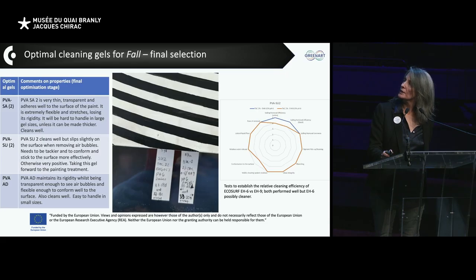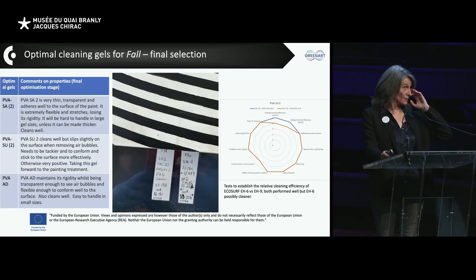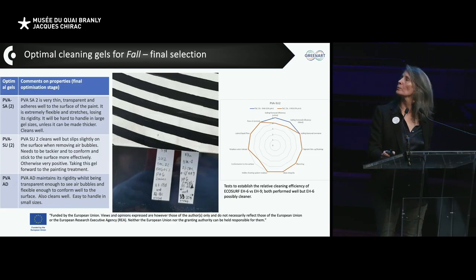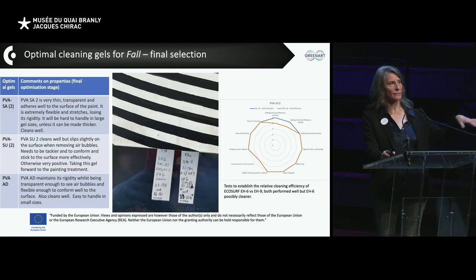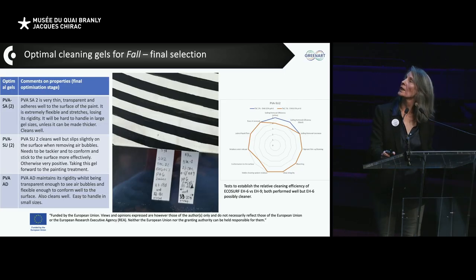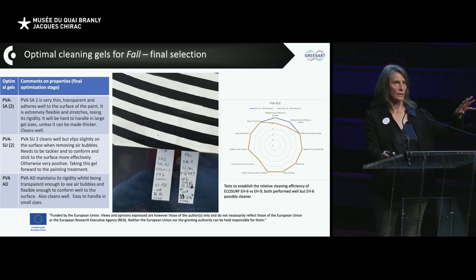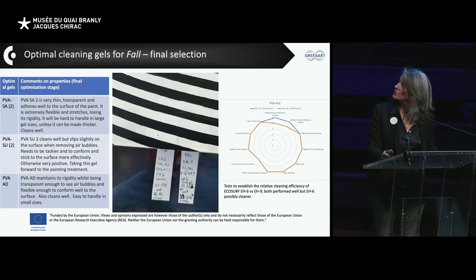And this is us, again, tailoring. This is the final stages of the tailoring. I call it the optimization phase, where we've decided on the aqueous system. We've worked around the pH, conductivity, citrate, chelator, surfactant space, and we've arrived in a good, efficacious system, and we then matched that with the best gel, hydrogel possible, and we've come up with the optimal system for that particular artwork. So maybe you can see some cleaning tests there.